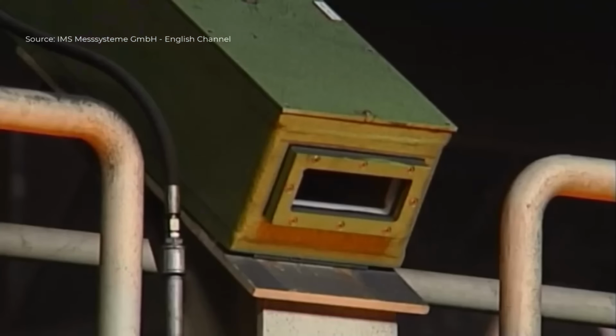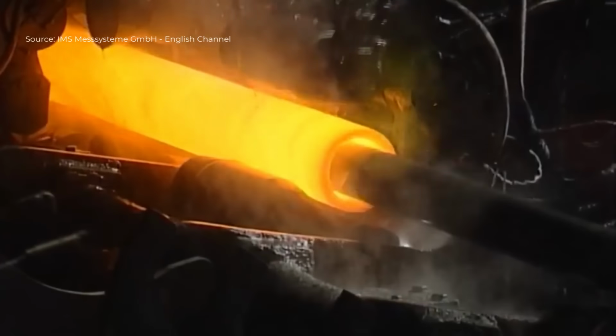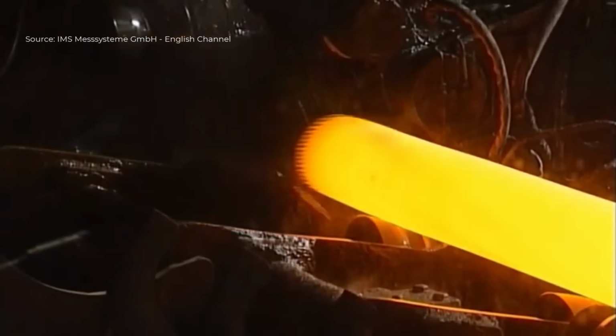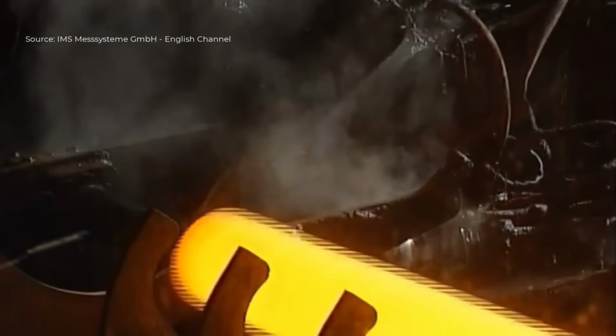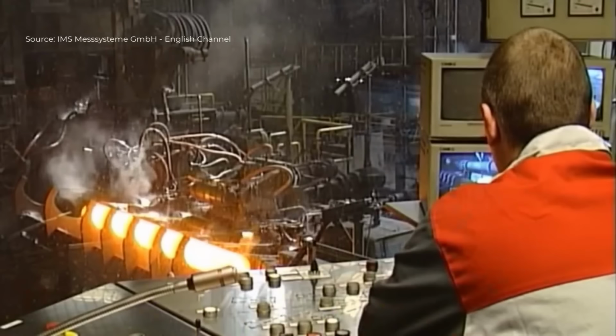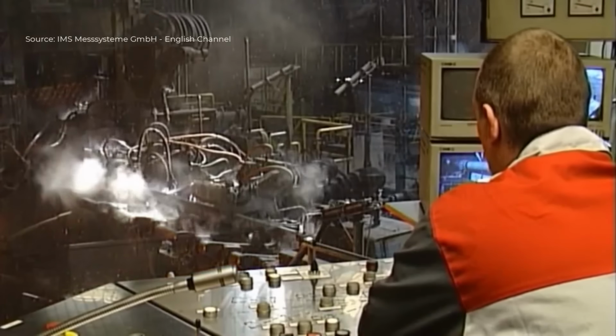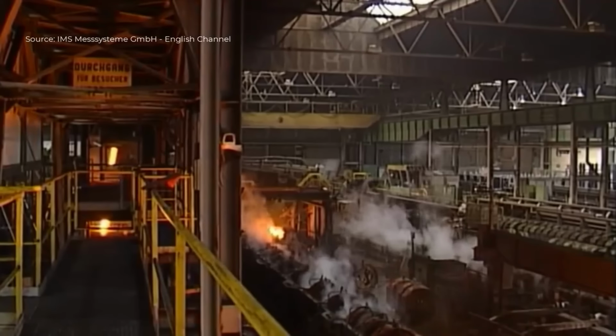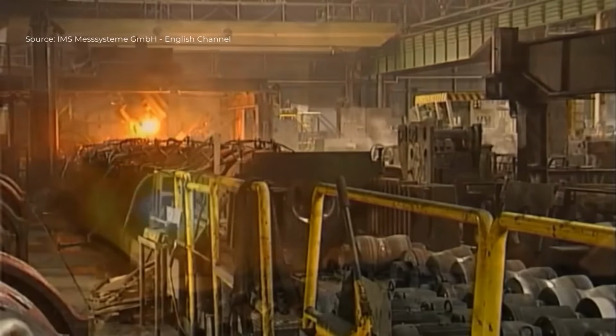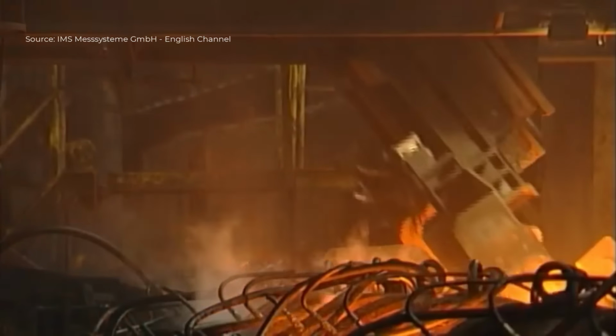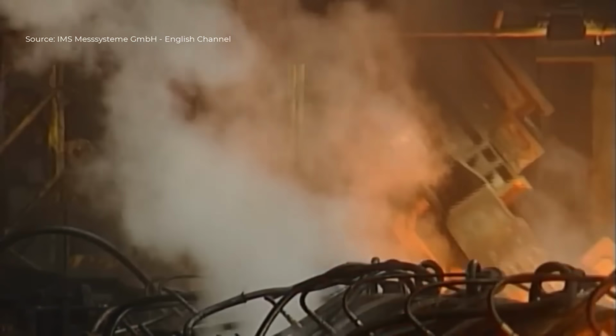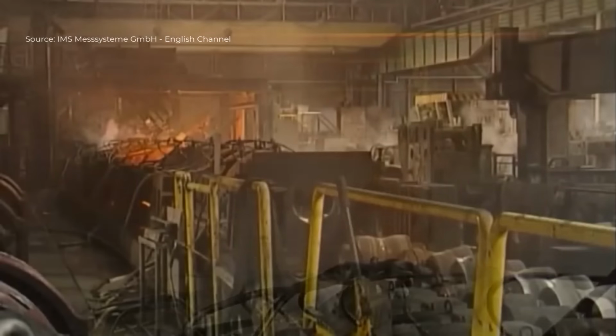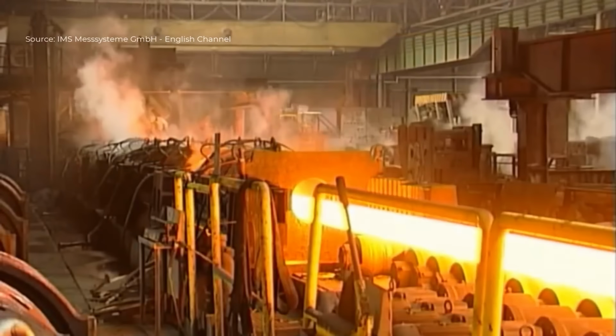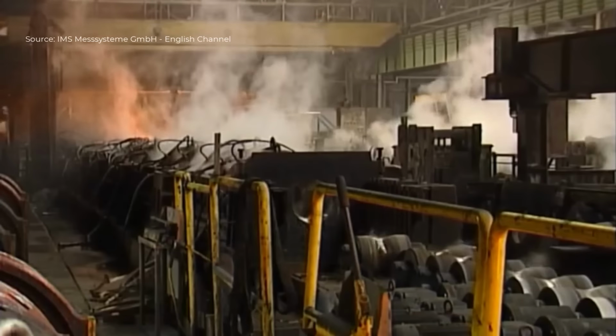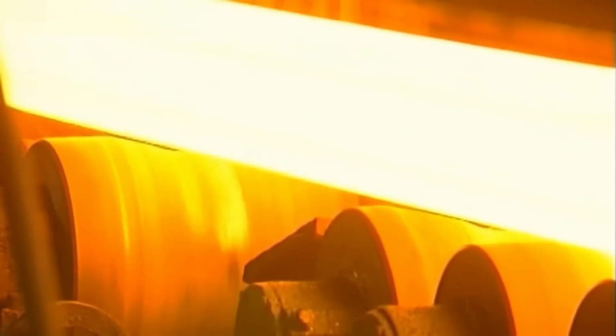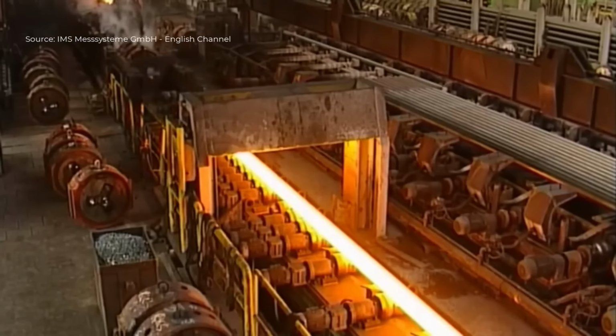The process involves two main types of sensors, the O-frame and the C-frame. The O-frame system features a 9-channel setup that enables double wall measurement. It encircles the tube and uses multiple ultrasonic transducers to measure the wall thickness at 9 different positions simultaneously.